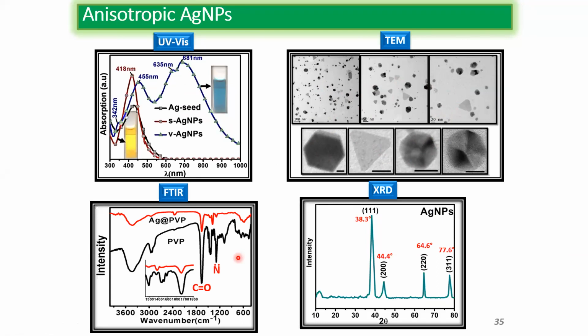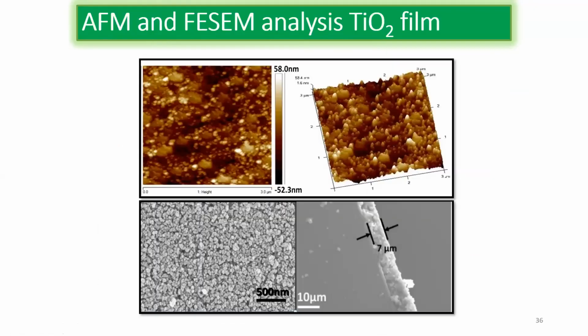These are characteristics we have to see before applying in the solar cell. When we use it in the solar cell, it should be PVP coated so that it does not react with the electrolyte we use. This XRD confirms that what we formed is a silver nanoparticle, and we compared it with the JCPDS data. These are AFM images on top and SEM images at the bottom.